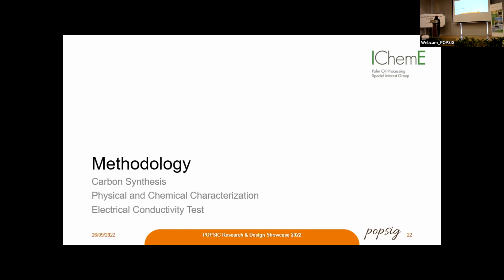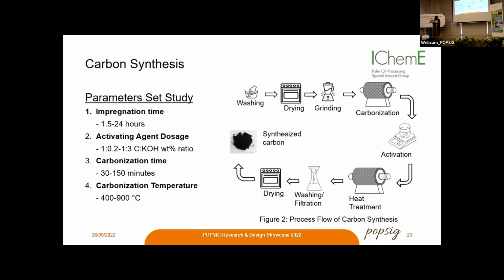Next is the methodology. The carbon synthesis consists of washing, drying, and grinding oil palm empty fruit bunch as a pre-treatment step before carbonization, activation through wet impregnation, heat treatment, washing, and drying to form a carbon sample. So the parameters studied are the impregnation time, activating agent dosage, carbonization time, and carbonization temperature.